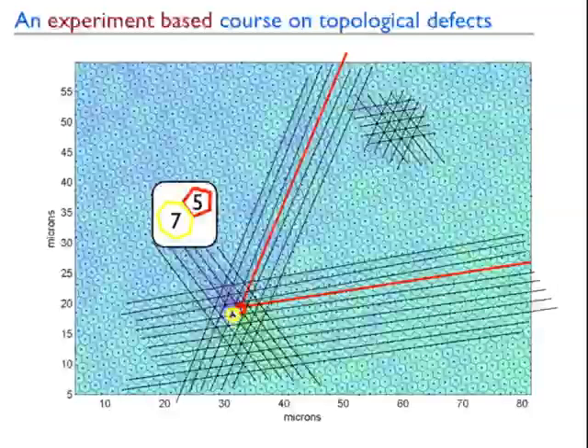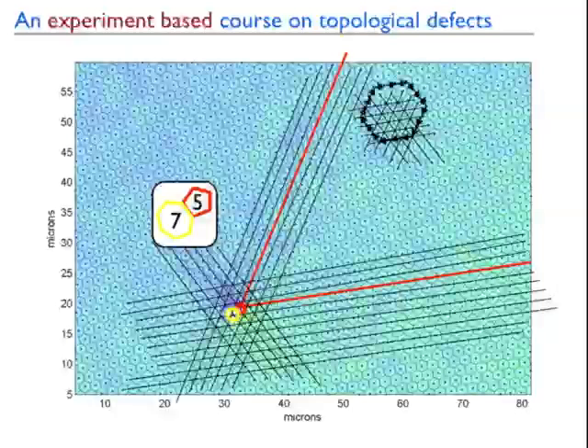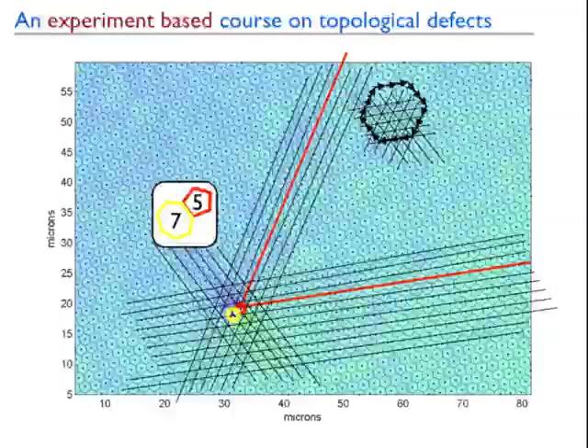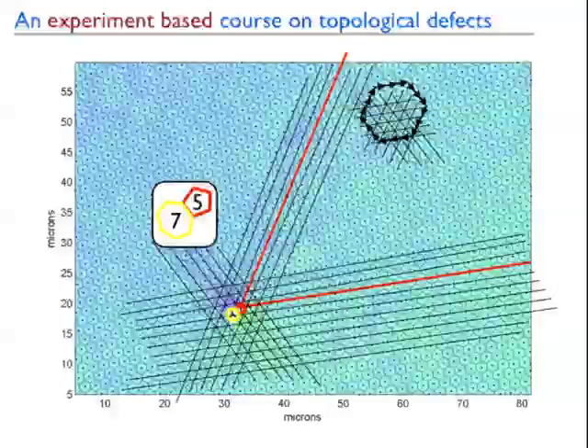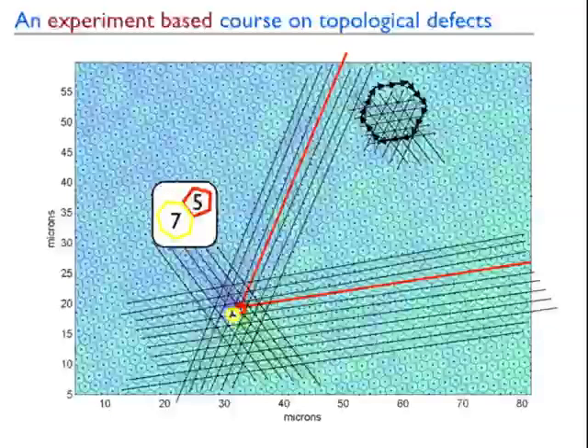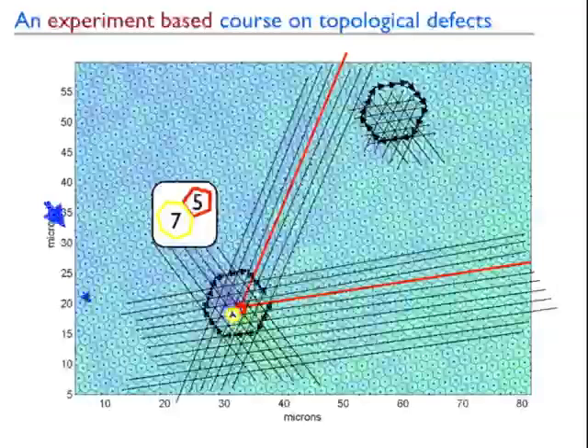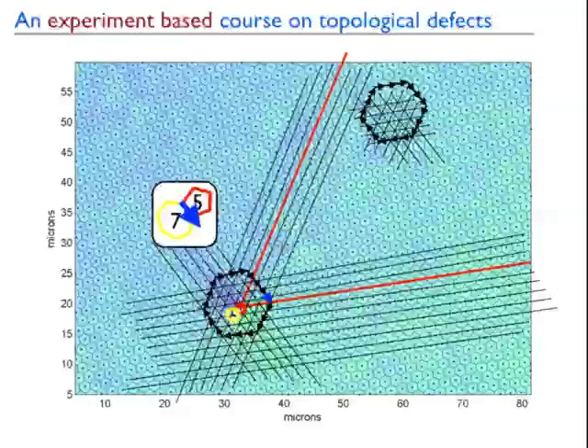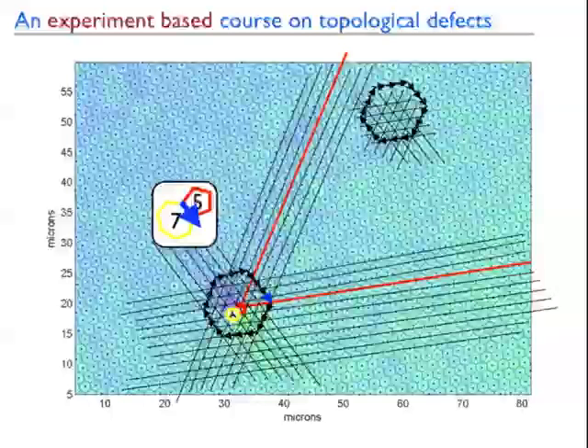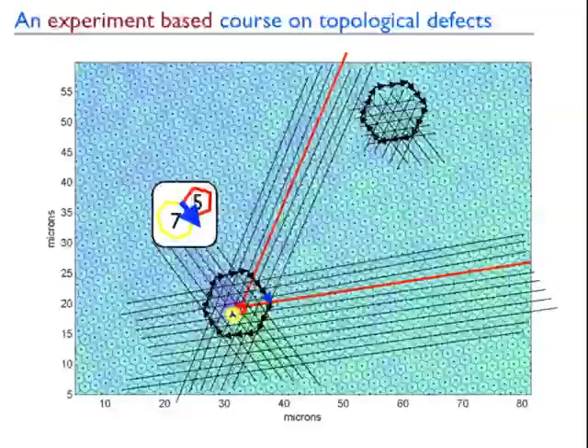You can tell that it's there by making a covering surface. The covering surface in this case is done by doing a walk around the particle. So, for instance, I take 3 steps this way, 3 steps this way, 3 steps this way, and then I repeat it. 3 steps at that angle, which is the opposite of that, 3 steps that way, 3 steps, and I close it. It comes back. If I do the same thing over here, I'm missing something. That's called a Burgers vector. And doing this construction, even if I don't look at this region, I could do this anywhere out here and it'd be missing this arrow. That's a Burgers vector, and it characterizes the dislocation, which is a topological defect.